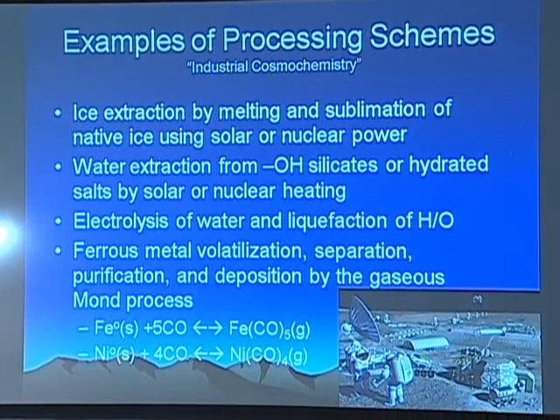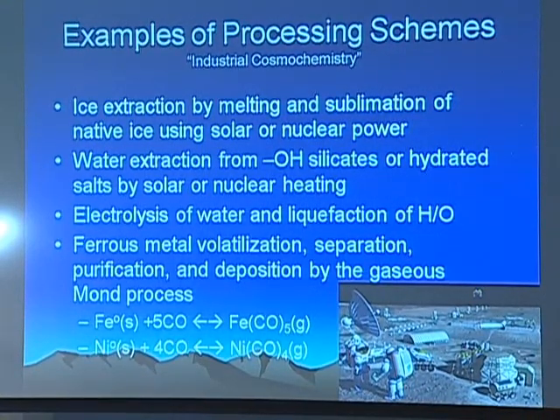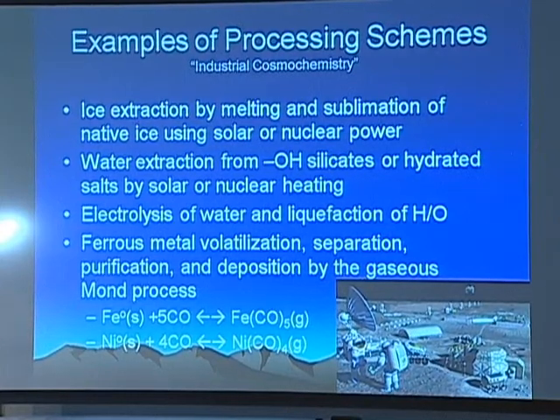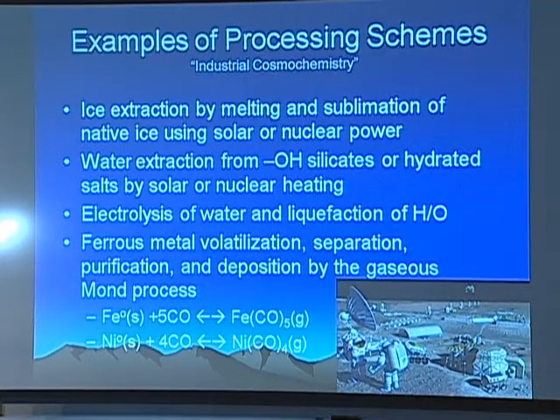This has been in commercial operation since over 100 years ago. The essential reactions here are that solid iron nickel alloys reacted with carbon monoxide gas at a pressure of about 100 atmospheres and 100 degrees Celsius forms gaseous iron pentacarbonyl and nickel tetracarbonyl, which have about the vapor pressure of liquid water. Those gases can then be separated by fractional distillation, and they can be selectively decomposed, for example, by passing them through a heated mold at 200 degrees Celsius to deposit single crystal deposits of iron or nickel that will fill the mold. This is a commercial process that's been in operation by a couple of companies in the United States.